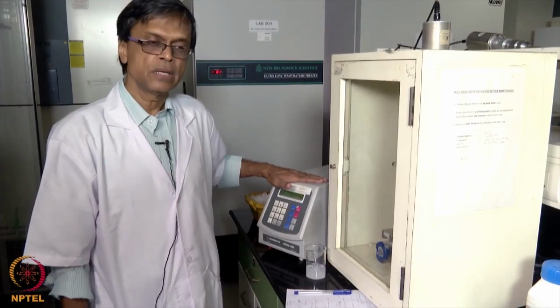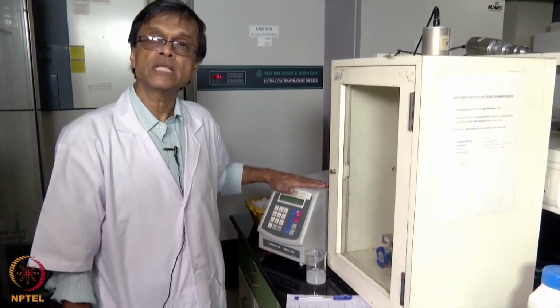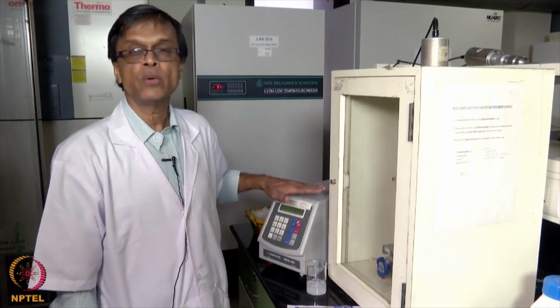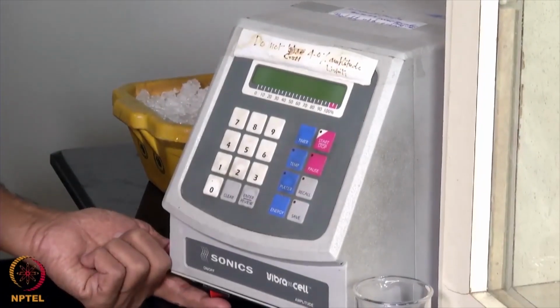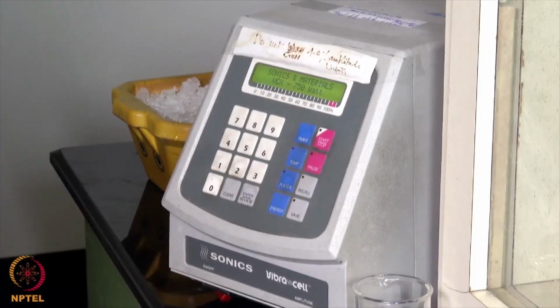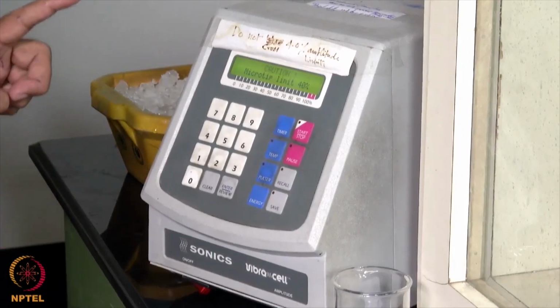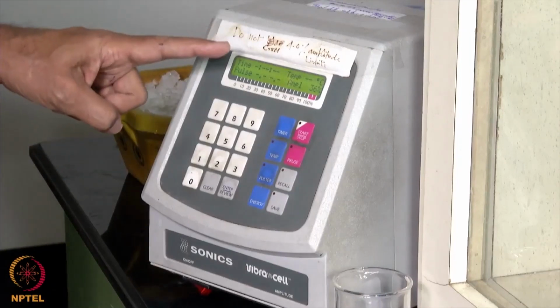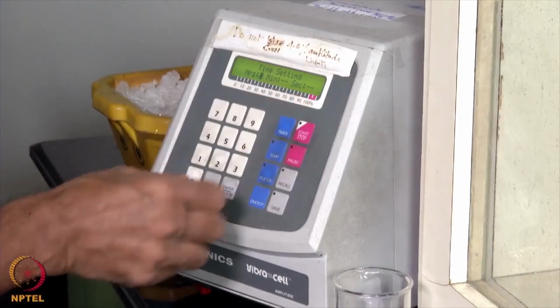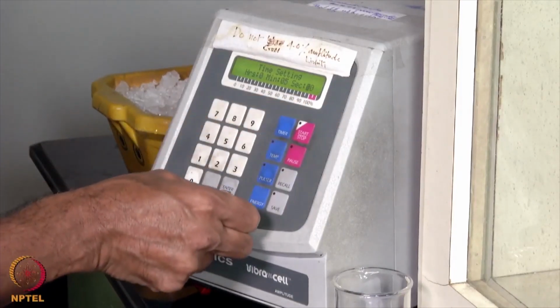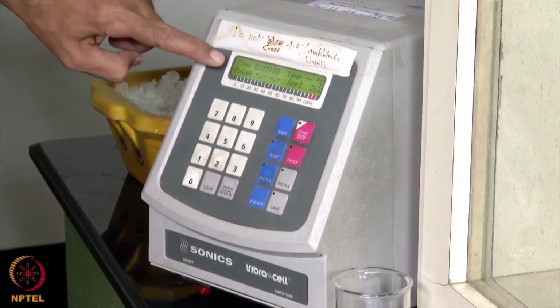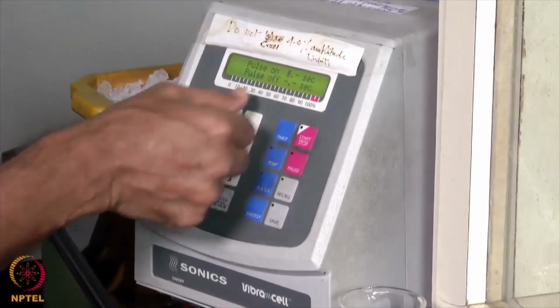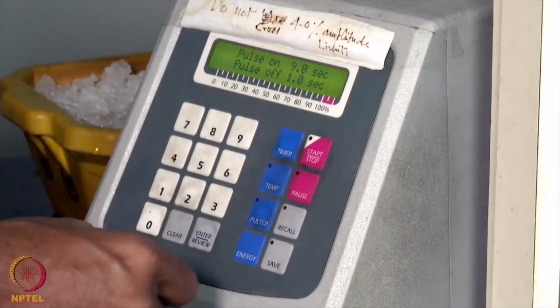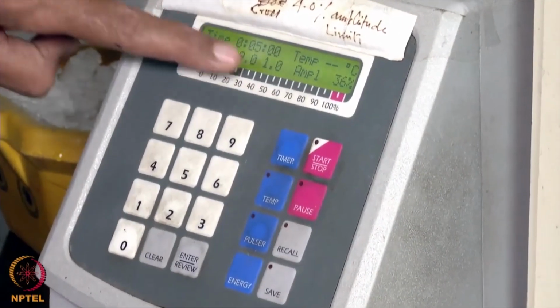So we need to set this control. We are going to sonicate for 5 minutes. It will not be continuous, there will be pulses and then stop, but every 9 seconds there will be pulse and 1 second there will be off. We will switch on the control unit of the probe sonicator. We will set the sonication time for 5 minutes. We have set the time for 5 minutes. Now we will set the pulse. Pulse on for 9 seconds. Pulse off for 1 second. Enter. So it's got pulse on for 9 seconds, pulse off for 1 second. It's going to be done at cold temperature.